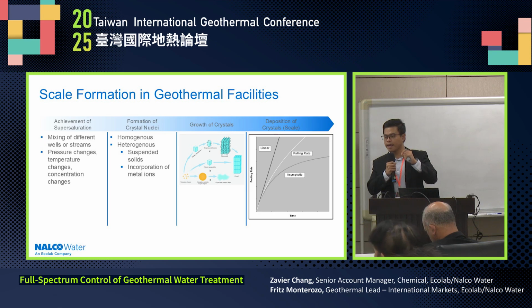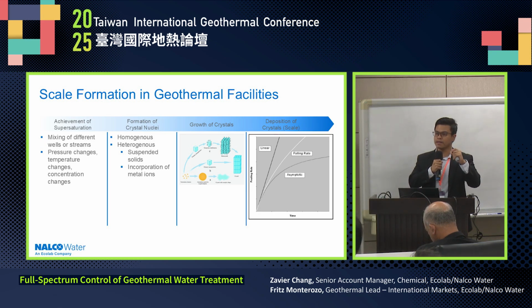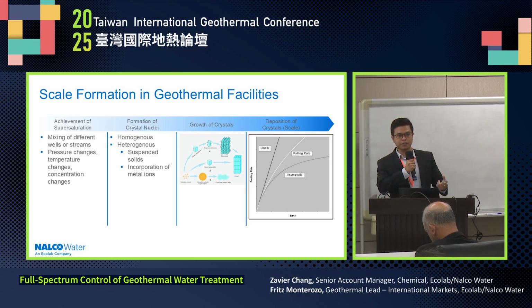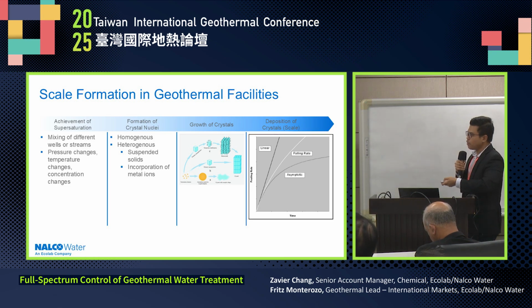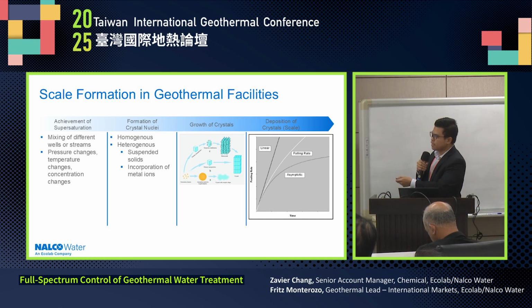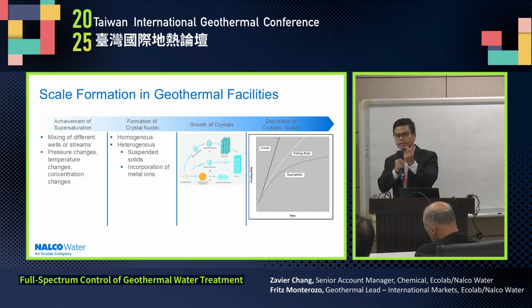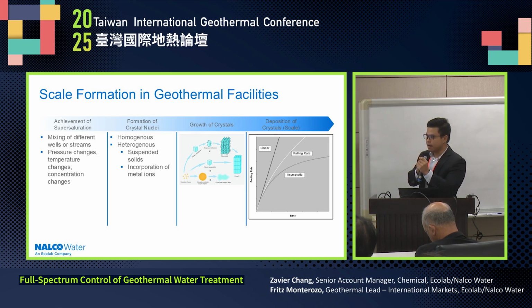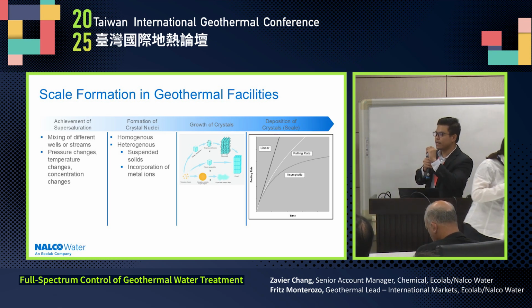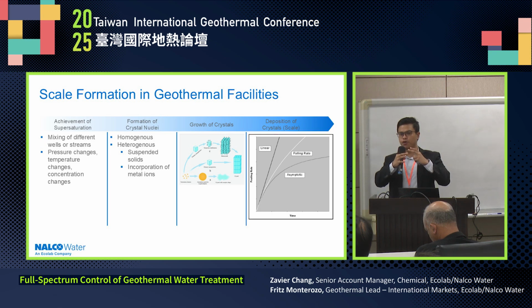of scaling. And if your saturation index is above 1, it means that your system is oversaturated. So higher than 1, you're almost sure that it will scale up. So your conditions should achieve supersaturation, and it will start with what we call nucleation. So there will be small particles in your system, and it will act as seed for your minerals to grow, or for your scales to grow.